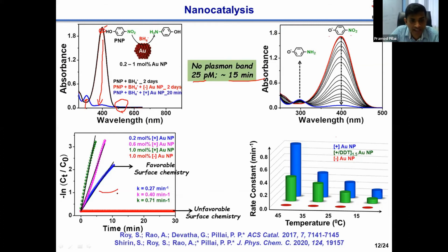So this is an important data which shows that even up to 1 mole percentage of the catalyst with an unfavorable surface chemistry is not able to make any catalytic transformation. Whereas with a 1 mole percentage of favorable catalyst, we are able to finish the catalysis within few minutes, like 2 to 3 minutes. So this is the power of surface chemistry.